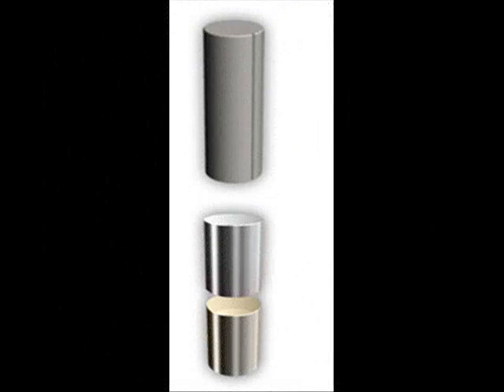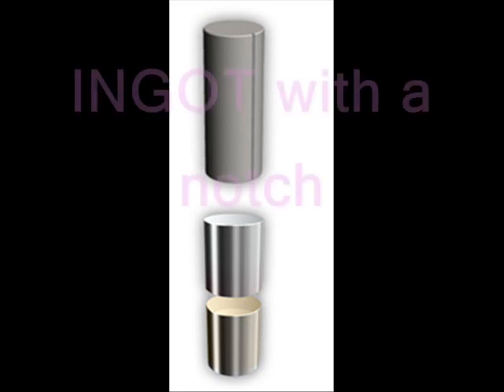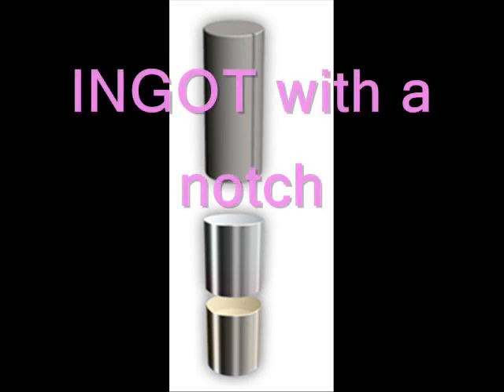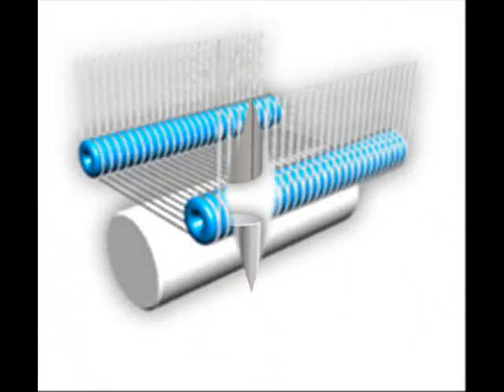Peripheral grinding. The ingot is cut to the specified length, and the periphery is ground to the specified diameter. Either an orientation flat or a notch is added to a part of the periphery to indicate the crystal orientation. The shape of the ingot following the completion of the peripheral process can be seen in the diagram. The diagram shows an ingot with a notch.